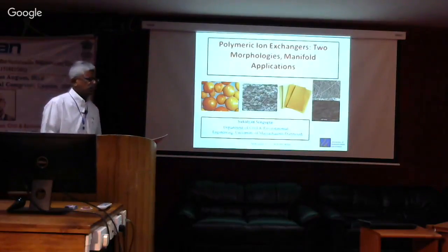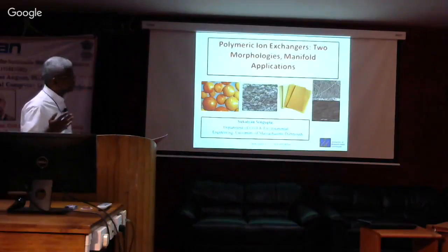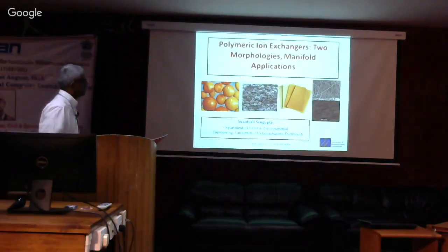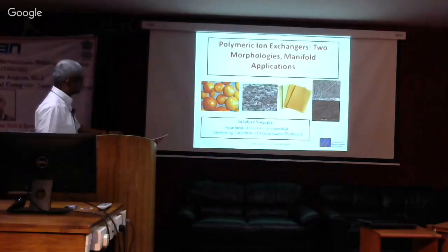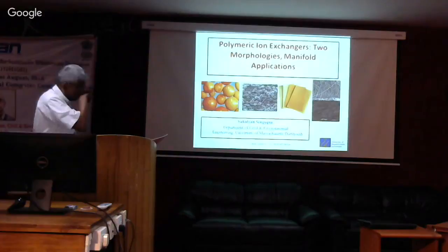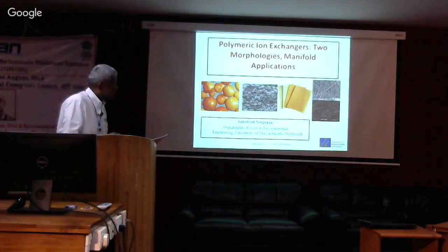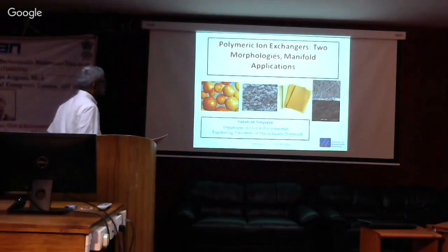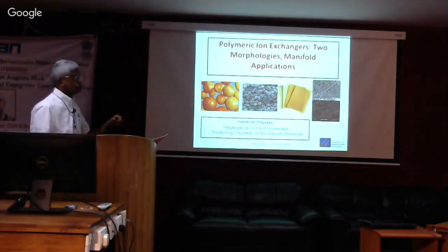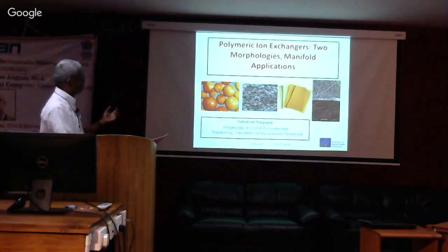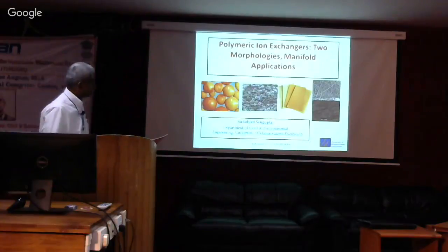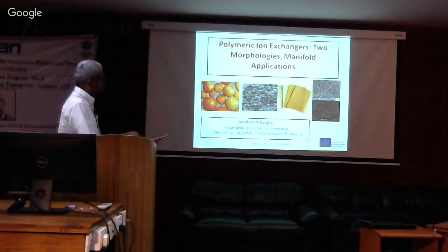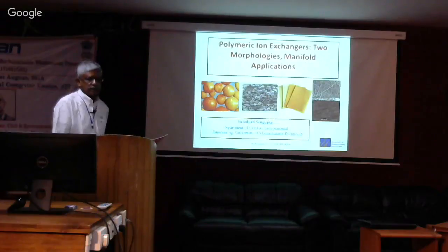You get a sheet which is typically maybe 0.3, 0.4, 0.5 millimeter in thickness, and it has these particles which do the job for you. And our job as synthesis chemists or synthesis engineers is to make sure that these sites are available, because there is always the danger that if you put too much Teflon, the Teflon would cover these particles. Okay. So that is one composite sheet, and the other is a fiber.